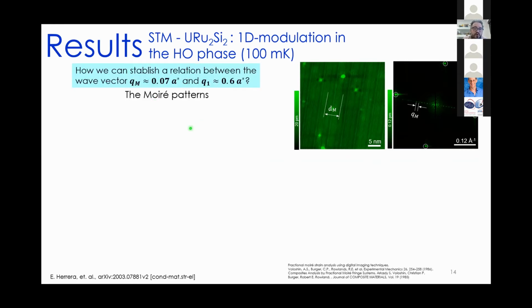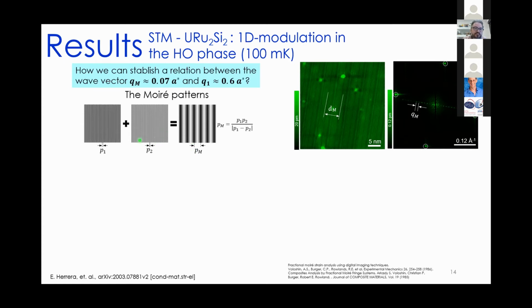So as maybe you all know, the periodicity of a moiré pattern depends on the periodicity of the initial patterns. For example, here, overlapping these two patterns originates this pattern, with a periodicity which is given by this expression. But a special thing happens between the moiré patterns if the initial patterns have similar periodicities, as I show you here. And if the initial patterns satisfy these conditions, the resulting pattern is known as a fractional moiré pattern. And the periodicity will be given by this expression that I put here. So we use this to analyze our data.